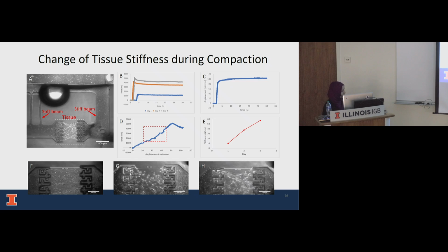Here is the data we have. Similar to what I showed before, as we pull on this stiff beam, we can record the force as a function of the displacement of these soft beams, and we can do it at different time points. We continued the experiment for 3 days. Here is the data for day 1 for the displacement versus time graph. And from the strain and measuring the force, we can also plot the force versus displacement curve.